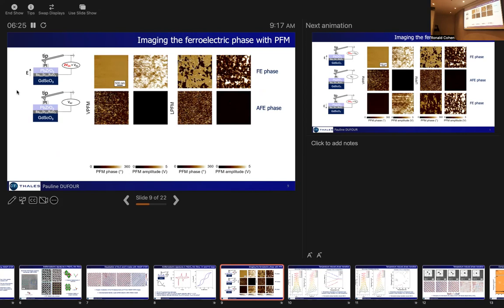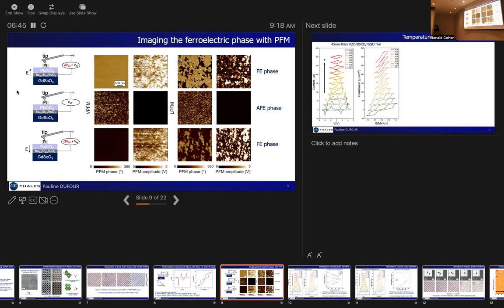And at 2 volts, we see that we have a well-defined phase and amplitude in the out-of-plane PFM, showing that the polarization is pointing downward. And surprisingly, you also have a well-defined phase and amplitude in the in-plane components, revealing that we have ferroelectric domains with different polarization components. We observed exactly the same pattern at negative bias at -2 volts, where this time we have reversed the polarization from downward to upward. And we also observe this same patchy pattern for the in-plane ferroelectric components.